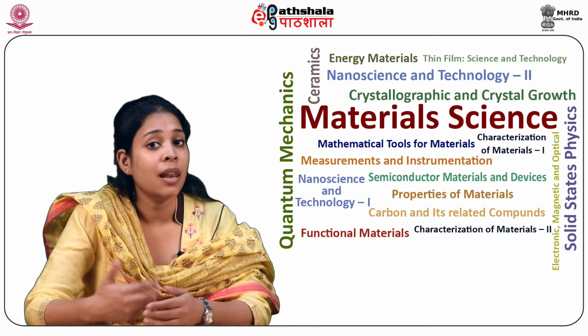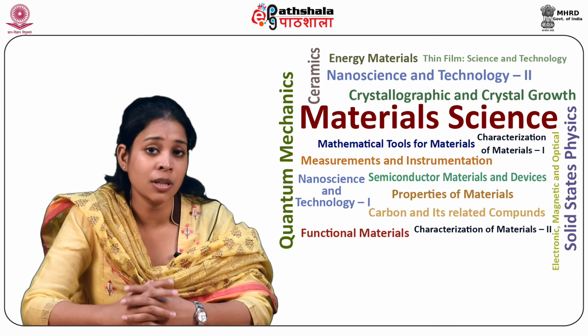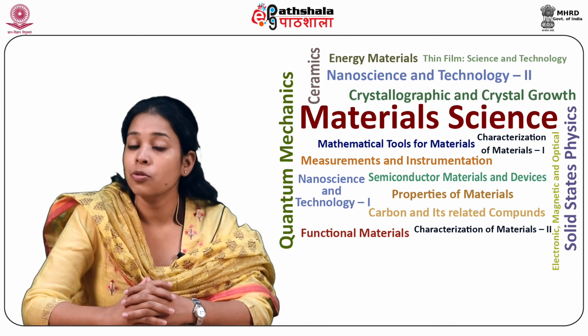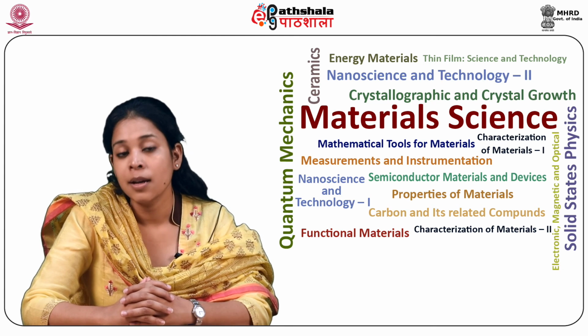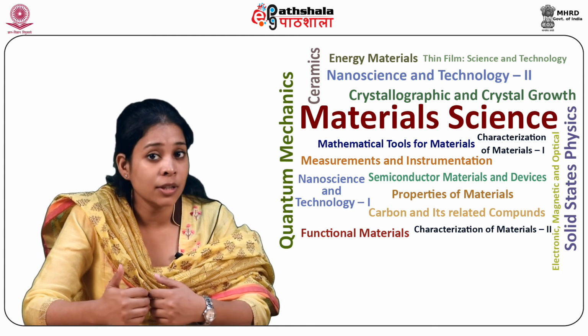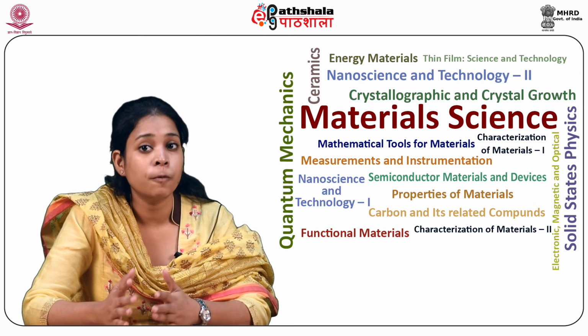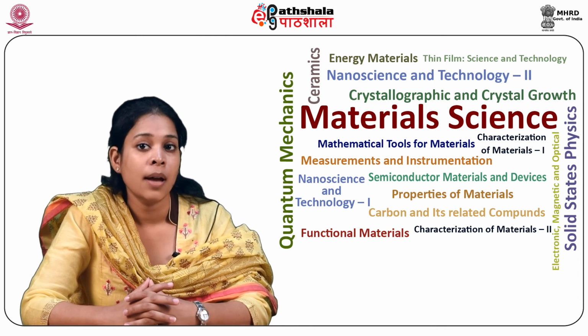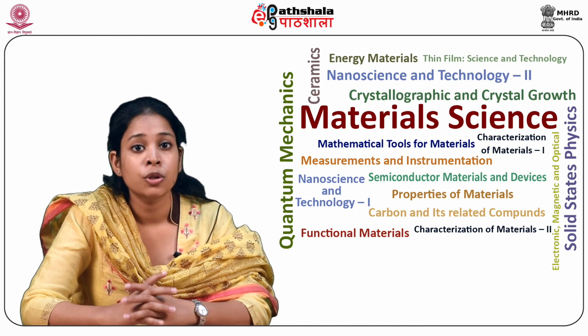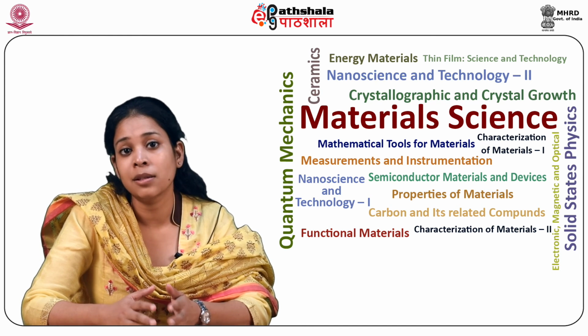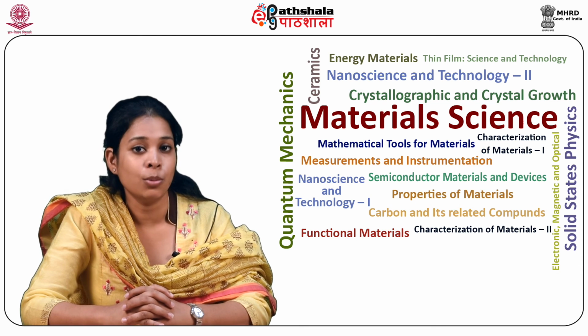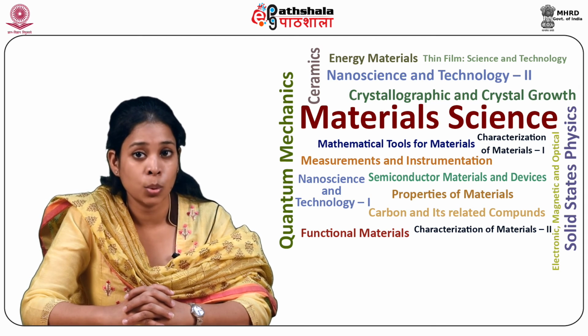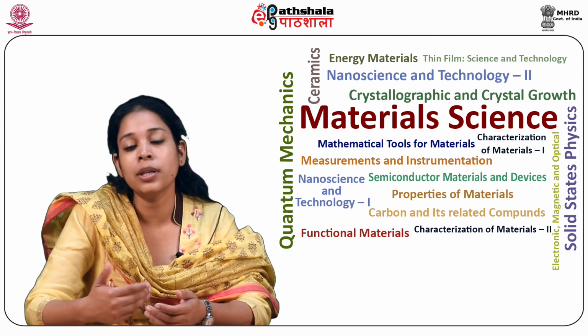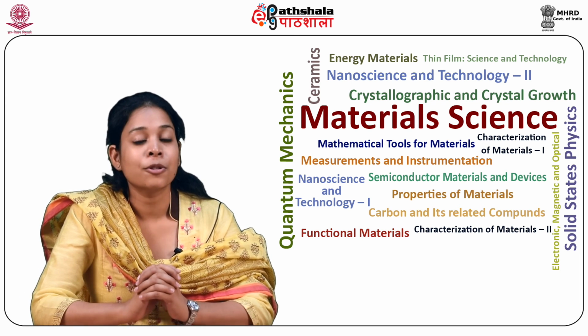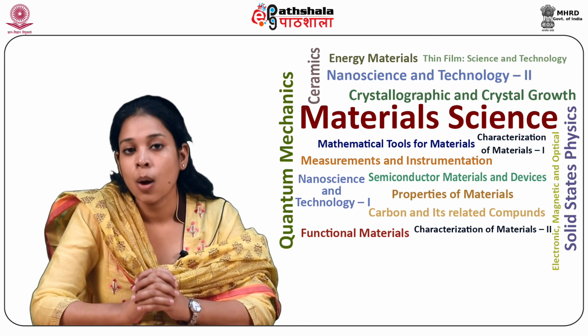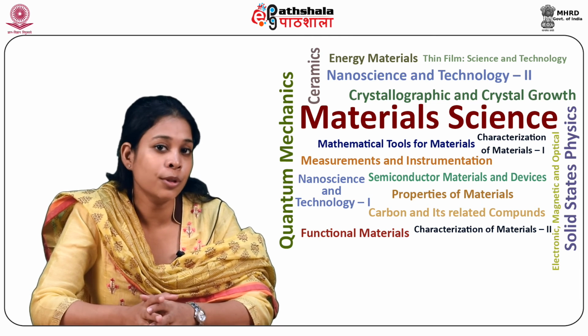This results in the large enhancement in the fracture toughness. For example, strength and toughness of alumina can be increased from 300 megapascal and 3 to 4 meganewton m to the power minus 3 by 2, to 900 megapascal and 10 meganewton m to the power minus 3 by 2 respectively in the zirconia toughened alumina. So students, let us summarize what we have learned in this module so far.